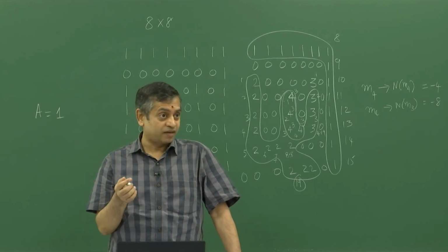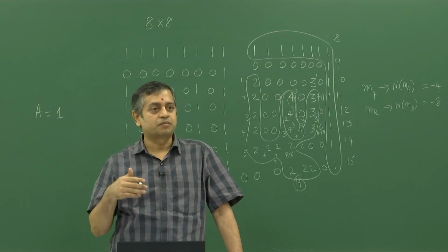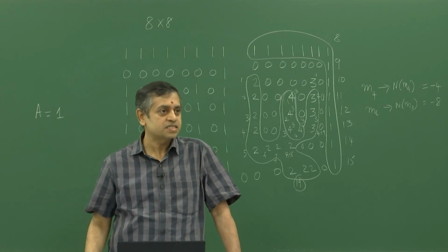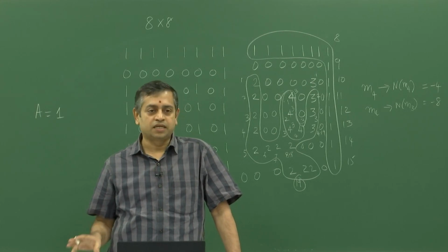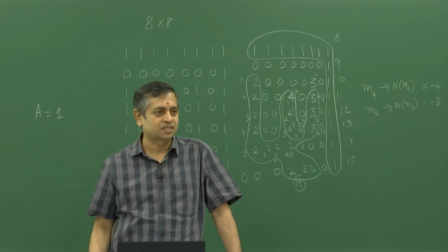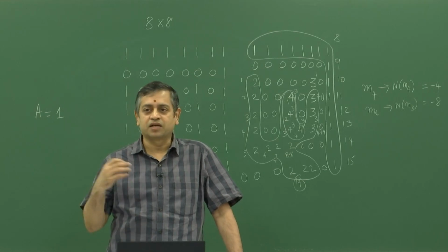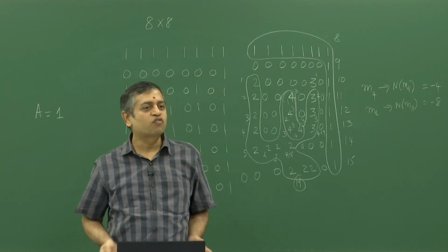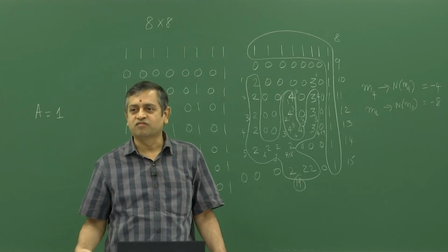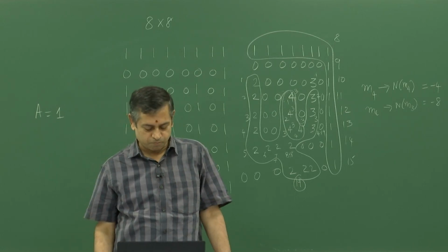So in some microstructures, whether a phase is percolating or not will tell which is the matrix phase. Typically the percolating phase is the matrix phase, and typically also the larger volume fraction is the matrix phase, but in some cases it is not. In nickel based superalloys it is because of the elastic moduli difference, or speculated to be because of it, but there could be other reasons. In some polymers, depending on flow properties, the more flowing one becomes the matrix and the less flowing, more viscous one becomes the island, what we would call a precipitate.